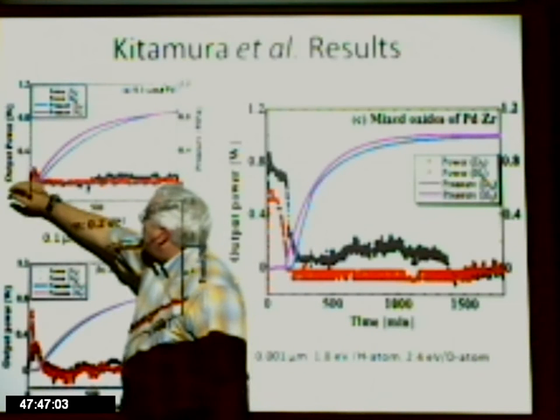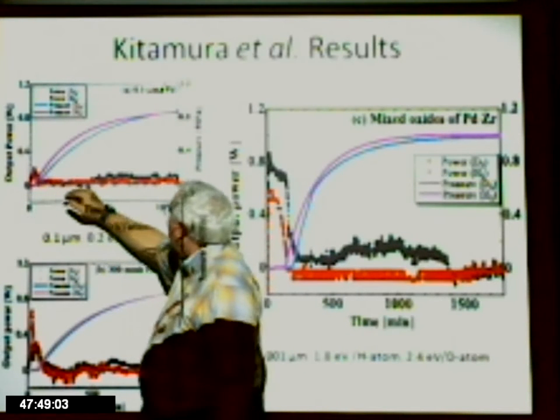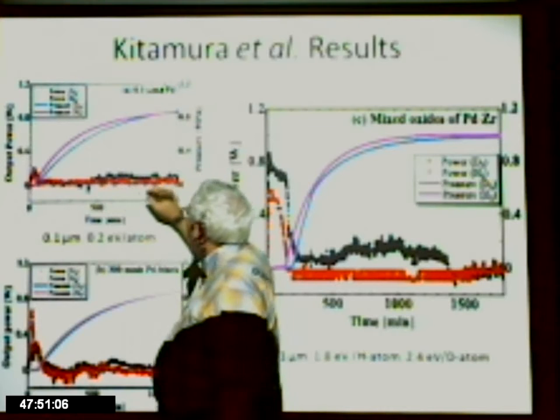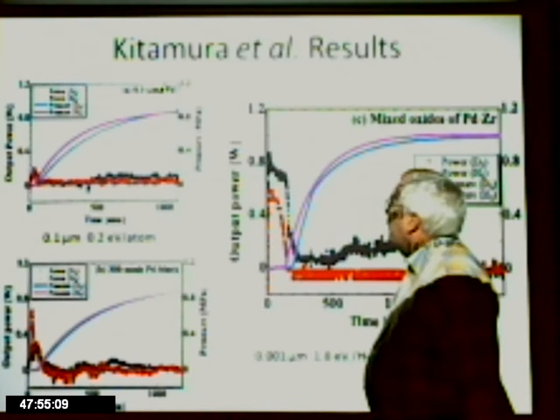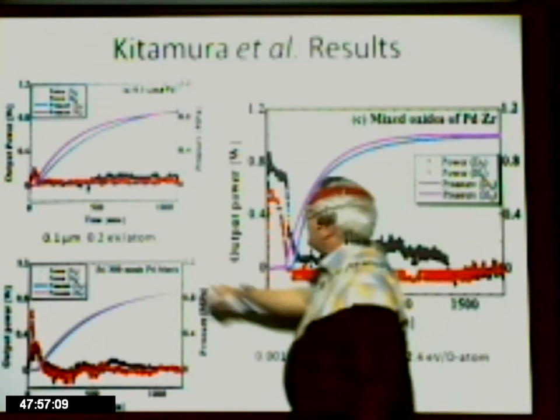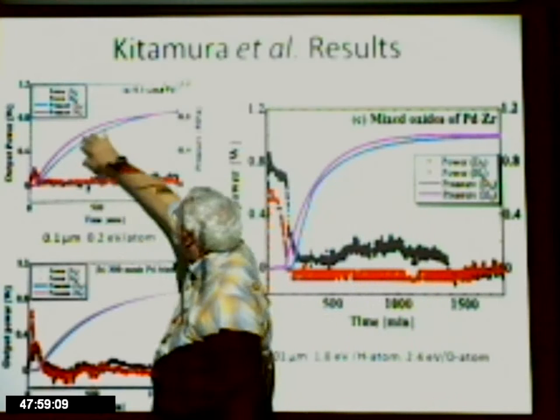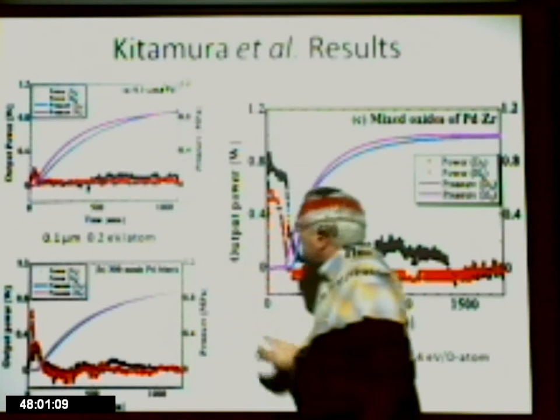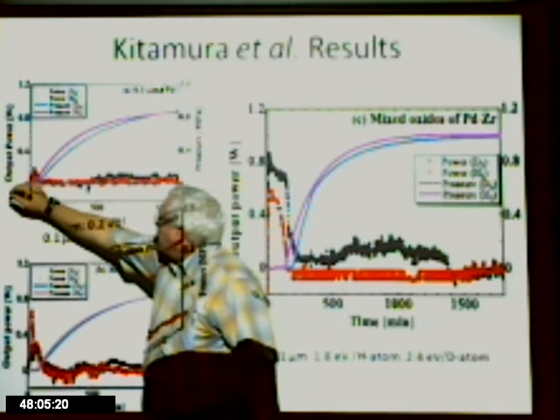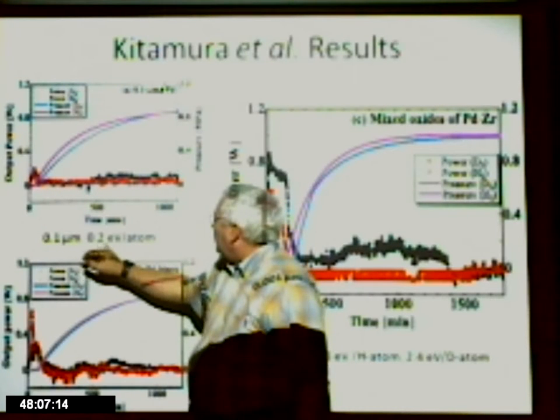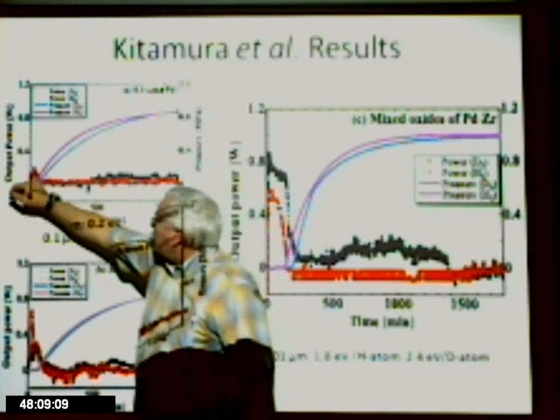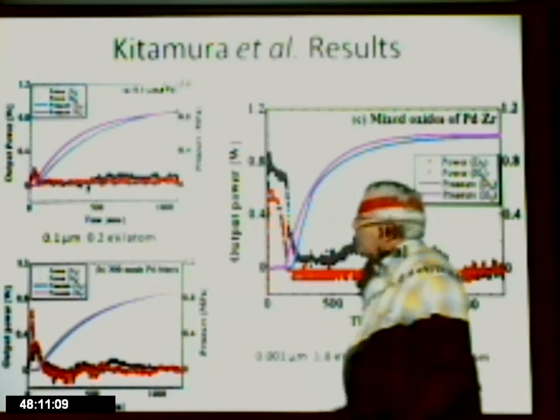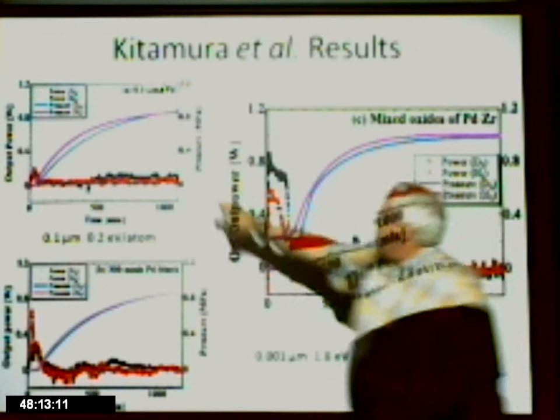Okay? And then after that saturates, it goes down to within experimental error of 0 on its calorimeter over the course of over 1,000 minutes. And the fact that this pressure loading goes up and saturates again is as expected. So here basically, this corresponds to about a 0.2 eV per atom heat of absorption loading on the palladium, about what it would be in a bulk. This is absolutely no surprise.